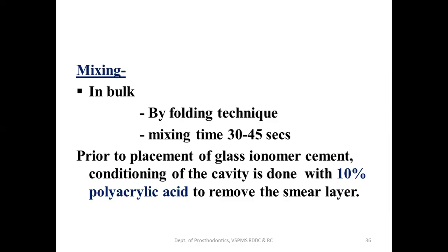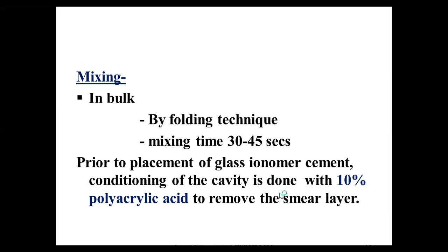Now the important thing is that the cavity that you are restoring should be conditioned before doing a restoration. So you will have to condition it with the help of 10% polyacrylic acid to remove any smear layer which is present, which may affect the bonding with the tooth enamel or dentin. That's why the smear layer should be removed with 10% polyacrylic acid. Then it is washed out and dried, and then you will have to do the restoration.